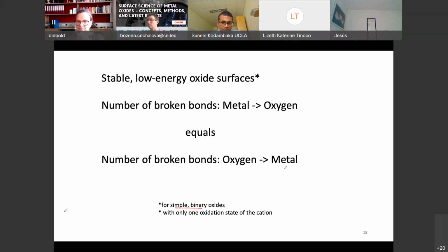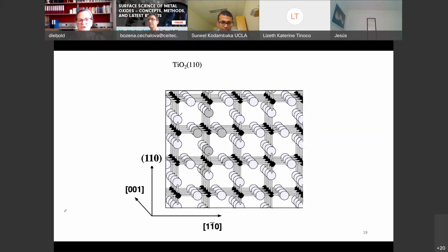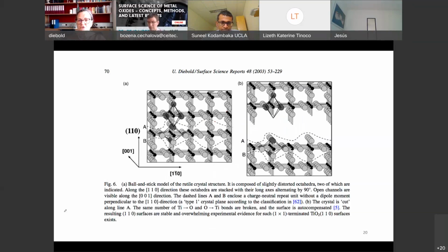So you break the same number of metal to oxygen as oxygen to metal bonds. Here you can see this TiO2 again. So I break 1 bond from metal to oxygen here, and then here I break some oxygen to metal. And here I break 1 bond from metal to oxygen if I make a cut like this. Here oxygen to metal bonds are broken, and this will give me a surface that's very low in energy. And that's really true.